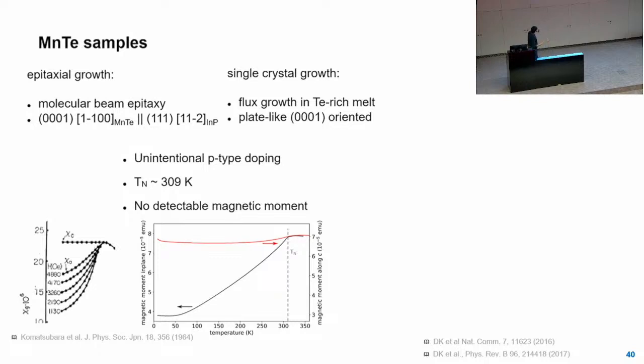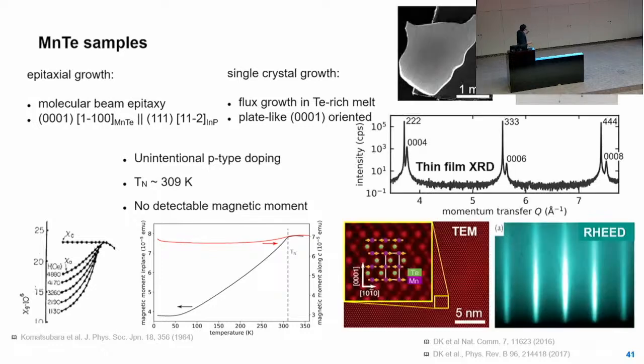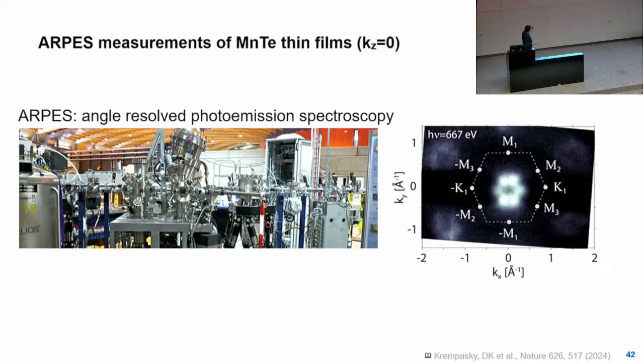We check that the magnetic properties are like they were previously found. I think we don't need to go into the detail here. We do the diffraction to see the symmetry. We said it is a hexagonal material, so we see the six-fold symmetry here. We also do transmission electron microscopy, where we directly see the columns of the atoms, and everything fits to the picture which we had before. There are some manganese atoms which should be magnetically ordered, and the tellurium in between. And then we need this fancy experimental equipment which actually allows us to measure these band dispersions.